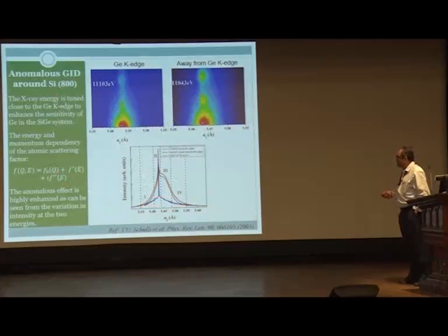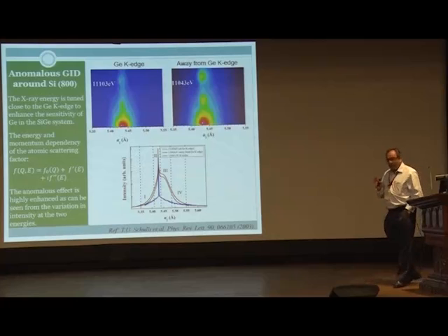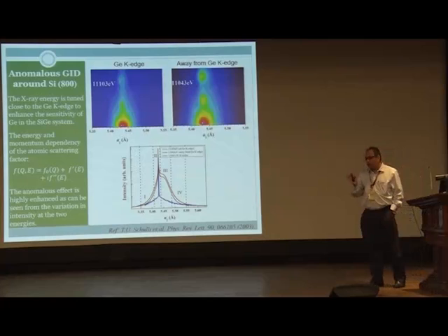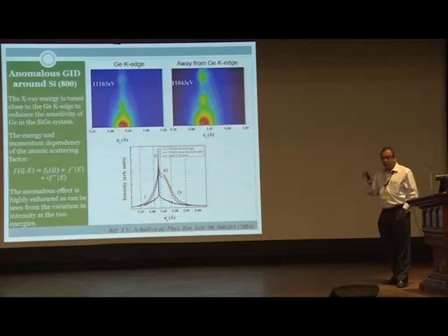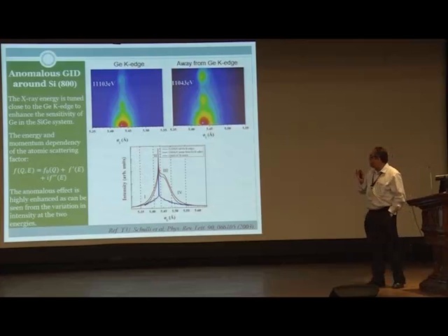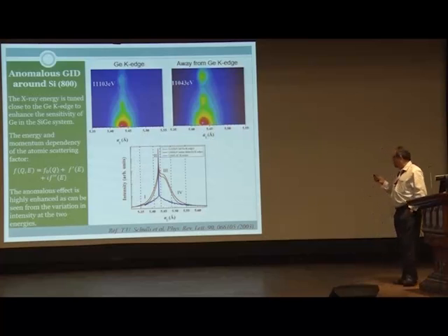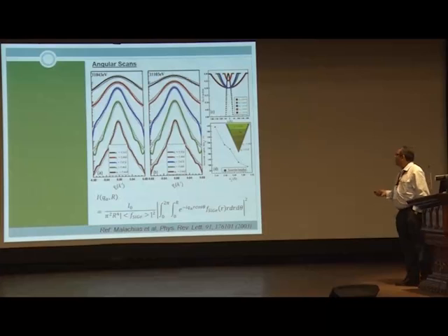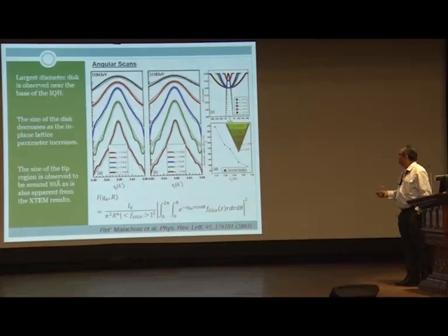But this time, for silicon and germanium, you are not lucky. These materials are not cancelling each other like gallium and arsenic. So you have to do a trick of anomalous scattering. You have to tune the energy of the X-ray beam so that we come to the absorption edge of germanium, and as a result, the scattering from germanium can be tuned. And by tuning that, one can find out this profile, and from there we could again find out the shape of the germanium inverted quantum dot, and also the composition of that.